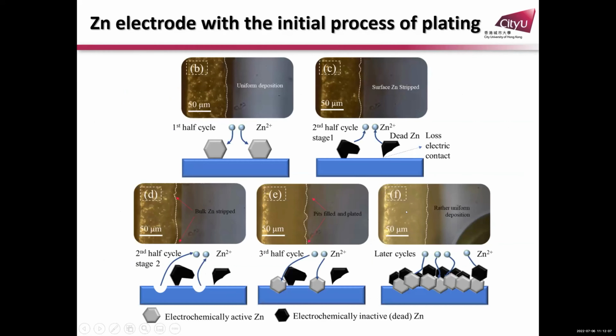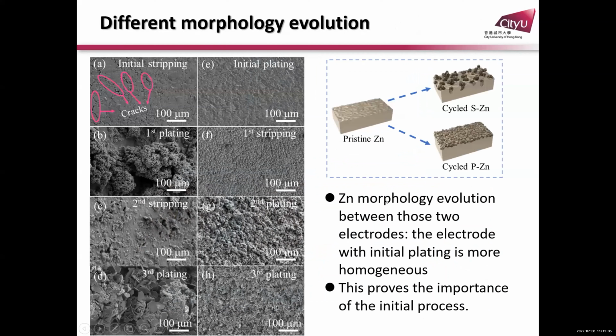If you go for a morphology study, even if the surface is not totally uniform, if for the first deposition you choose a very suitable current, even starting from a non-uniform surface you get uniform deposition first. Then after a few cycles, you see the surface is still very uniform, although you still have some dead zinc. So this is very straightforward information.